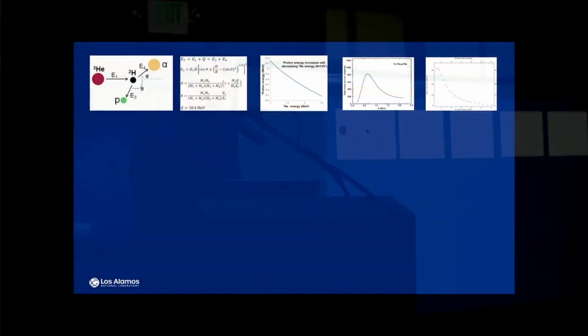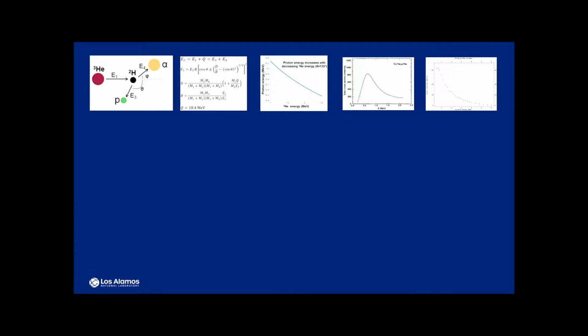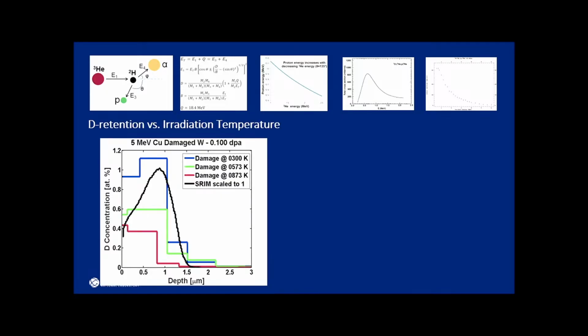Now, going back to the tritium side. There is a very beautiful reaction people use either way: you can use deuterium to analyze helium-3, or you can use helium-3 to analyze deuterium. Now, obviously, tritium is a very different monster to take care of, so we cannot do tritium in our setup. We use deuterium as the surrogate for tritium. So there is this very nice reaction with a large cross-section to measure the deuterium retention. If we damage tungsten to the same damage level at different temperatures, we can see the deuterium retention drops, because the temperature does reduce the damage level quite a bit. This change was not observed in the thermal conductivity, but it was picked up by the retention measurement.